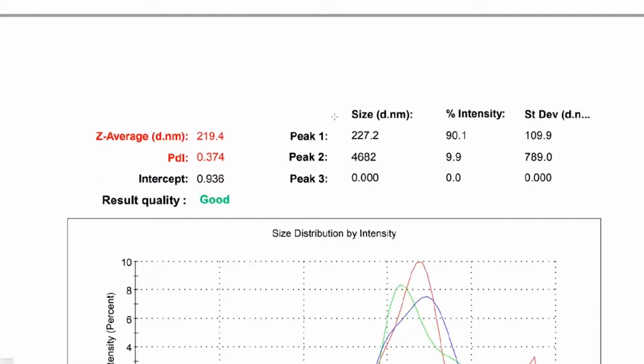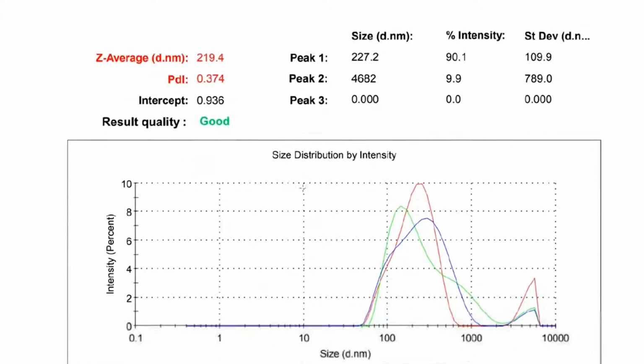Okay, Jeff, let me show you a few things from the paper that'll help present the size and how we analyzed the material and demonstrated that it was attached onto the surface. This is our DLS analysis, dynamic light scattering, of the particles. You'll see the main peak is at about 230 nanometers. We do have some larger particles, you'll see a peak out here. When you do DLS, this can just be a few particles, but these are 3 different traces, and you can see we're pretty much in the 200 to 300 nanometer range, and that's really where we want to be.